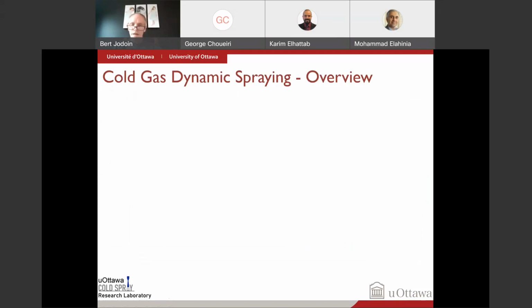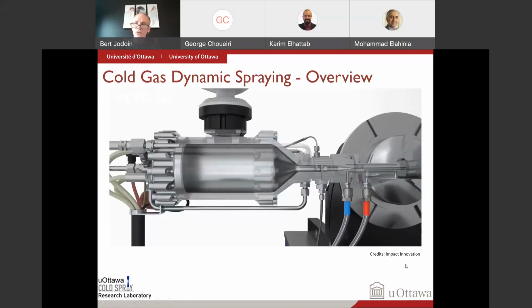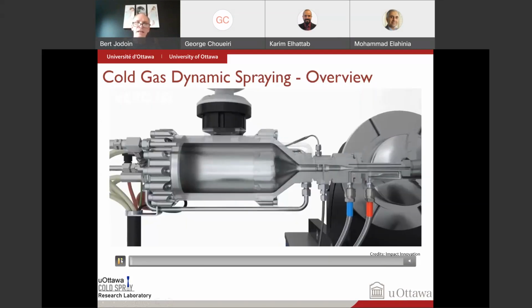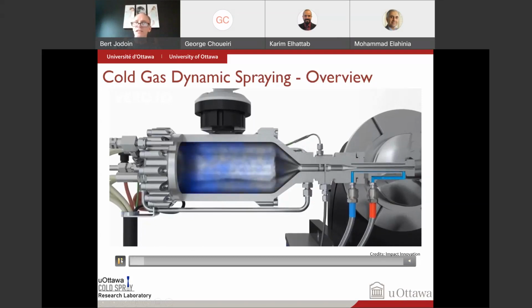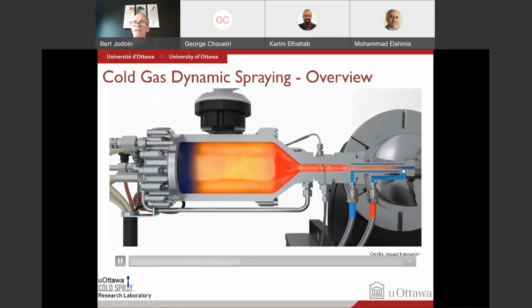Sorry, let me go back. If you want to accelerate the gas to a much faster velocity, what you can do is you can preheat the gas prior to injecting it here. In cold spray, we can preheat it up to 1,000 Celsius. This increases the energy content of the gas and it's going to become warmer and it's going to expand to a higher velocity.